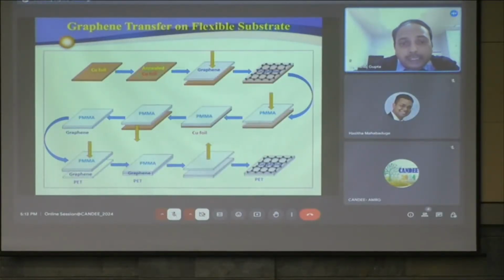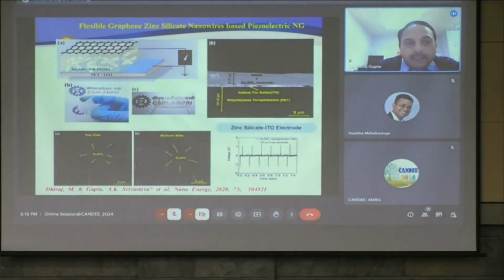So we did the wet transfer method: we etch out the copper by a wet chemical route, and then we transfer this graphene on the PET substrate. This copper foil was etched out through the solution, and then this is the final diagram of the device. These silicate nanowires are randomly distributed in the PDMS polymer matrix. This was randomly oriented, and this is the graphene we transferred on the PET substrate. First we transfer on the PET, and that was mechanically integrated into the device. And you can see here that the nanowires are randomly aligned.